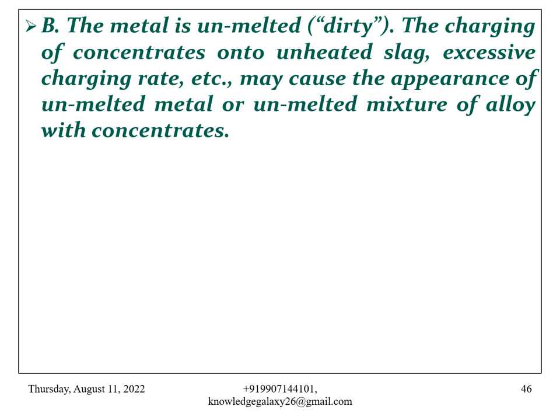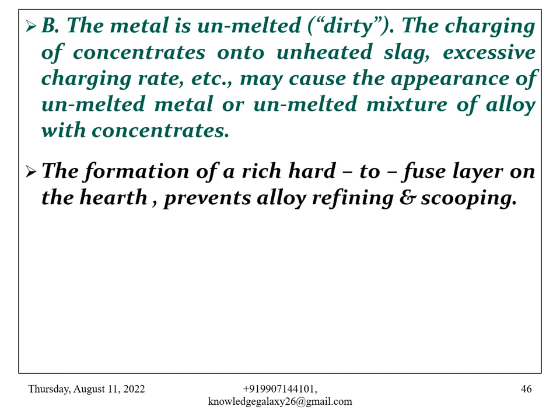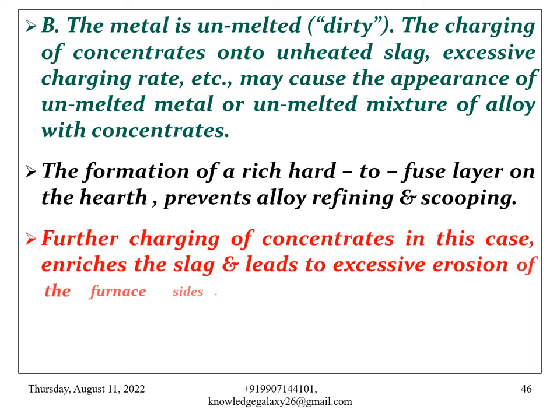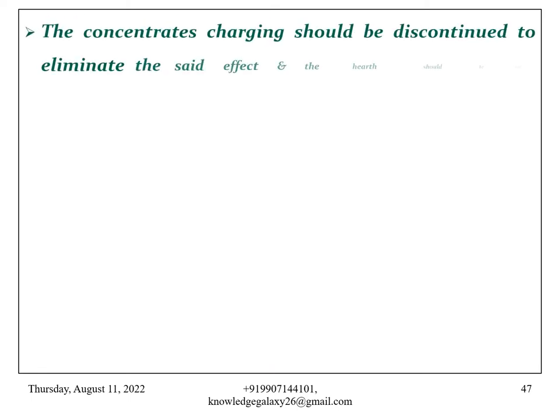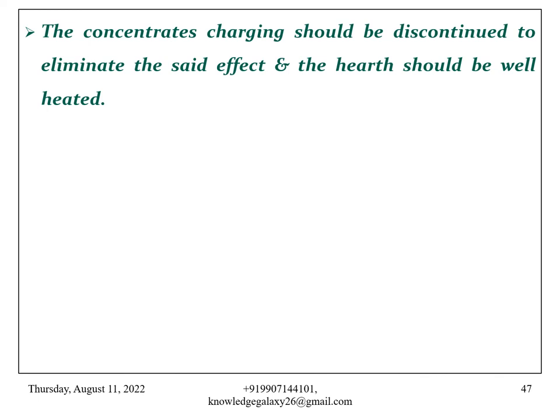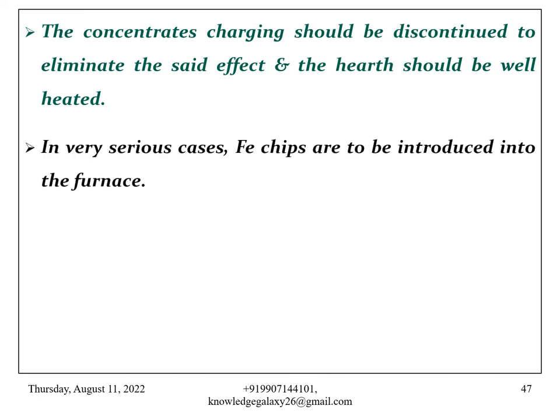Second, the metal is unmelted, that is dirty. The charging of concentrates onto unheated slag, excessive charging rate, etc. may cause the appearance of unmelted metal or unmelted mixture of alloy with concentrates. The formation of a rich, hard to fuse layer on the hearth prevents alloy refining and scooping. Further charging of concentrates in this case enriches the slag and leads to excessive erosion of the furnace sides. To rectify this problem, the concentrates charging should be discontinued to eliminate the bad effect, and the hearth should be well heated. In very serious cases, iron chips are to be introduced into the furnace.